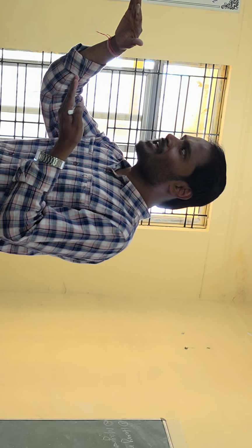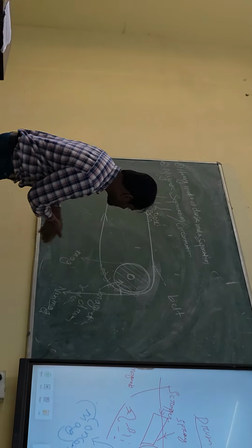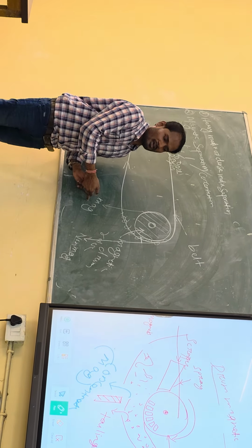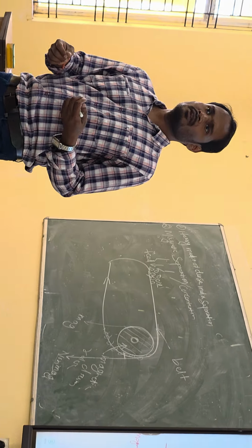So what will happen? Separation efficiency will be less, because suppose there are many layers. Just imagine there are many layers of solids. Top layer is magnetic, bottom layer is magnetic, but the in-between layer is non-magnetic. So non-magnetic particles will be trapped in the magnetic minerals, and they will come with the concentrate. You understand my point? So in the mag fraction also non-mag will be there, and in the non-mag fraction also mag will be there if there are solids. But if it is a slurry, they will be in dispersed form, individual. So it is easy to separate mag and non-mag in slurry form.